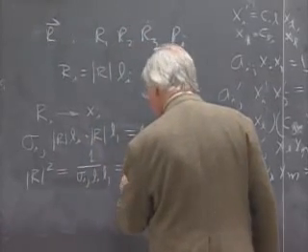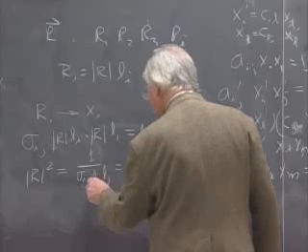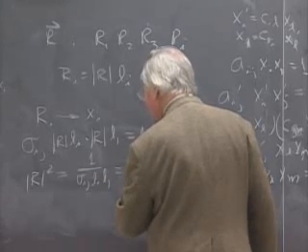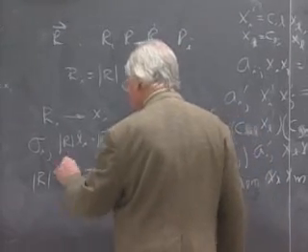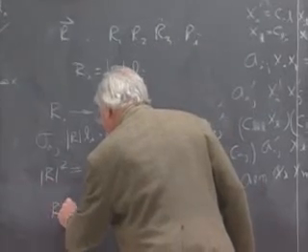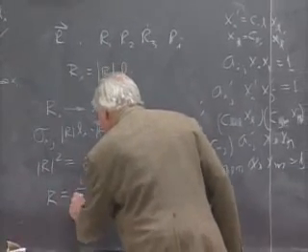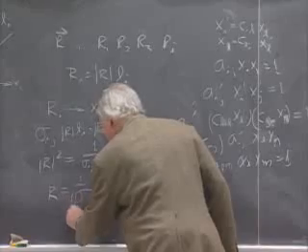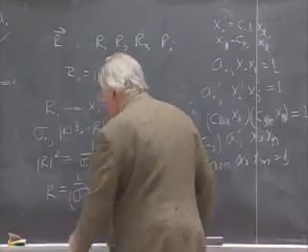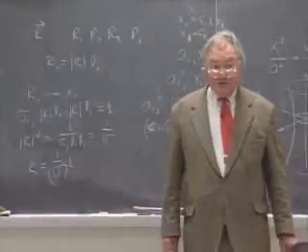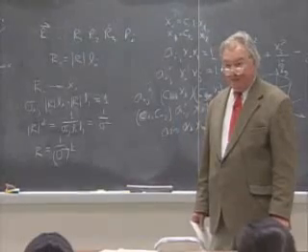The value of the property that will occur in the direction specified by the direction cosines L_j is such that the radius of the quadric is going to be equal to 1 over the square root of the value of the property in that direction. Okay?